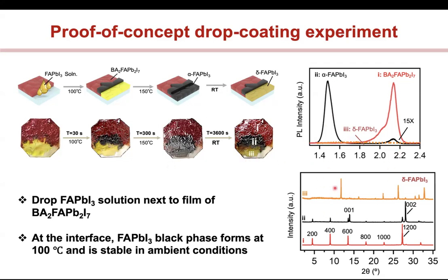And in fact, the X-ray diffraction patterns show that this is really an alpha FAPI phase. And we can now do it at lower temperatures, 100 degrees C, as compared to 150 degrees C, which was the original temperature. And it's also stable. It doesn't come back to its yellow phase.